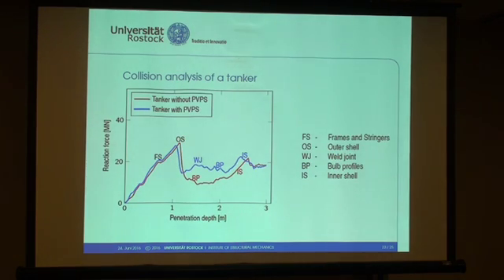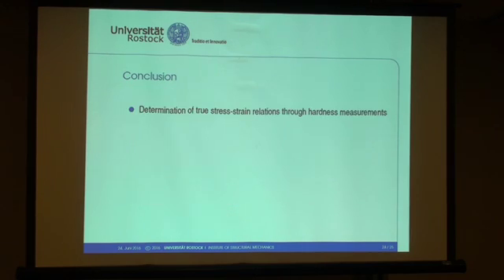And I just want to exemplarily show 2 force displacement curves of 2 different collision analyses of the tank ship. One without PVPS, the typical double hull design, and one with PVPS. Integrating these force displacement curves into the energy, and from these energy displacement curves, an increase of 20% can be determined. 20% increase of the energy absorption of the double hull structure by the PVPS. And with that, I want to conclude my presentation.